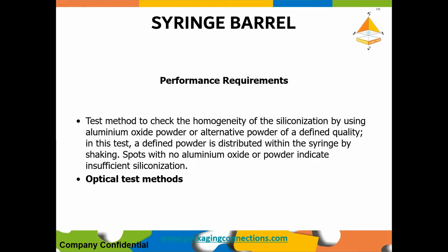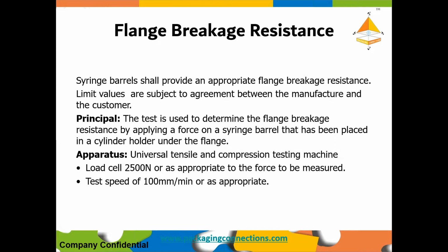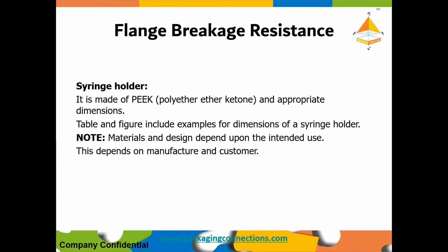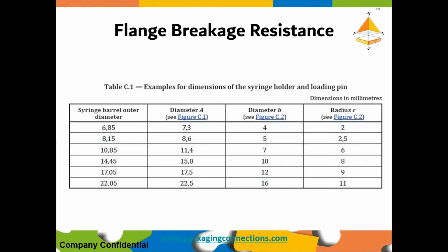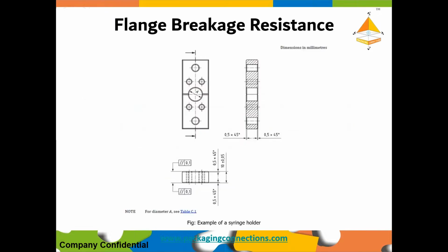So how do we find out? We can spray aluminum oxide powder and see how it is sticking, or we can use optical methods where we can see. We can use flange breakage. Flange breakage is very, very important. So we can test it using the universal testing machine at different speeds. We can use a syringe holder where the syringes are capped and it is made out of PEEK in a particular dimension. The dimensions again are recommended in the ISO. This is how it is.